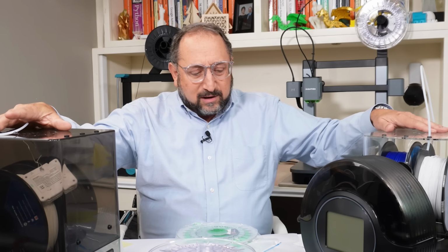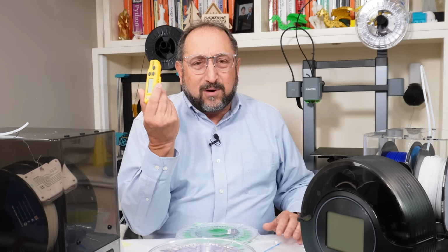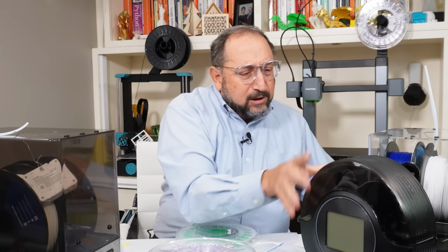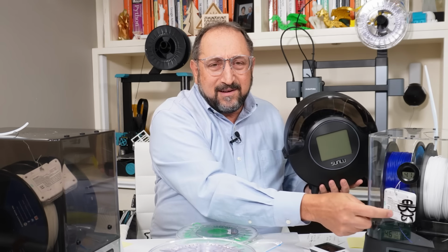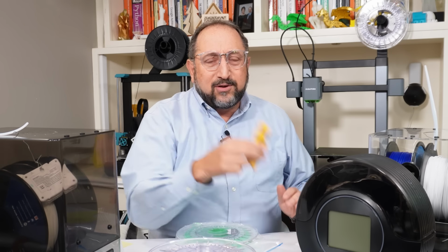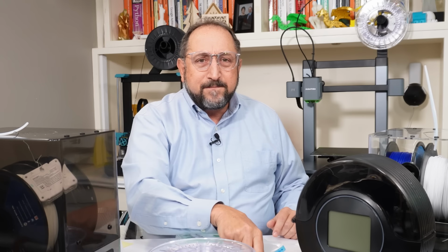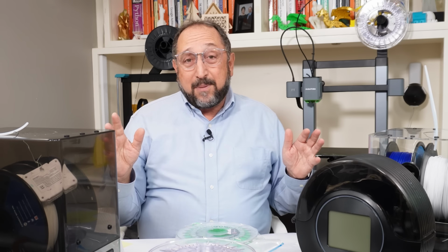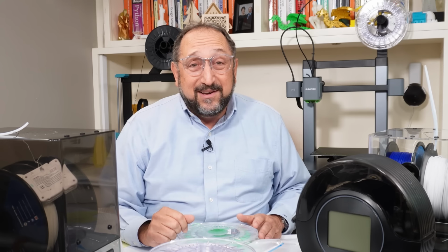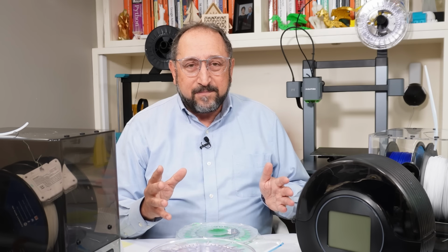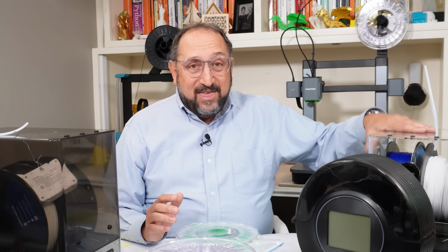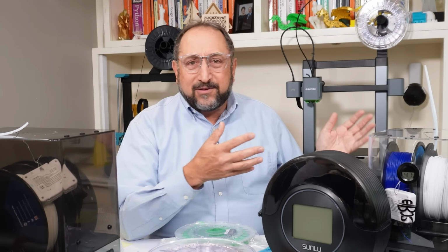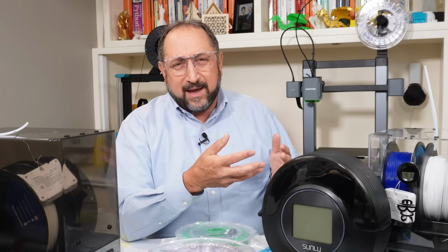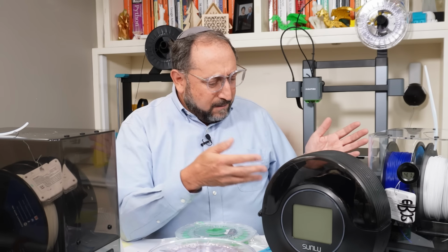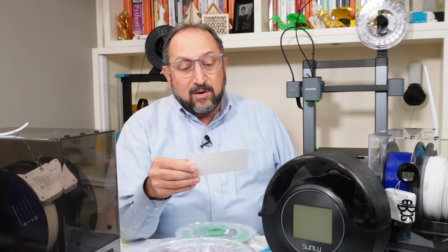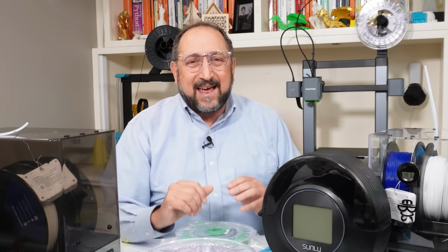But in these larger enclosures, what I found by measuring temperature a lot of different ways, including putting a sensor right in the middle, including using a thermometer at the top, at the bottom, is that the temperature can vary by 10, 15, or 20 degrees Celsius. That's a lot. And so in this case, this print dryer from SUNLU, and this is an old model, so I'm not reviewing it. I'm not comparing it to their current model. But this particular one, in general, was running about 7 to 10 degrees hot.